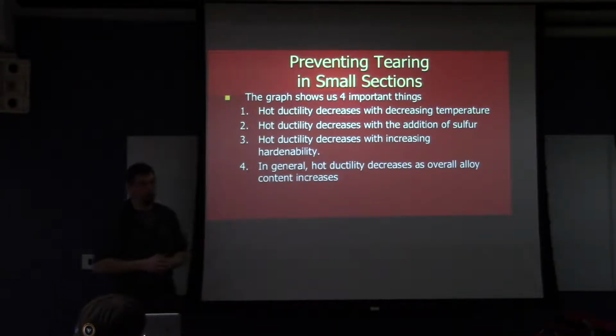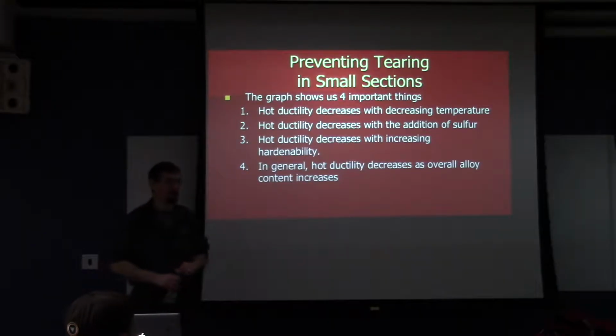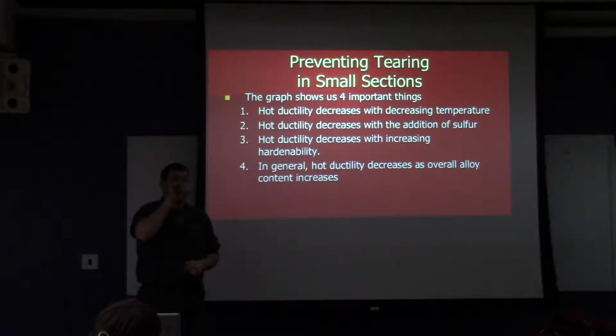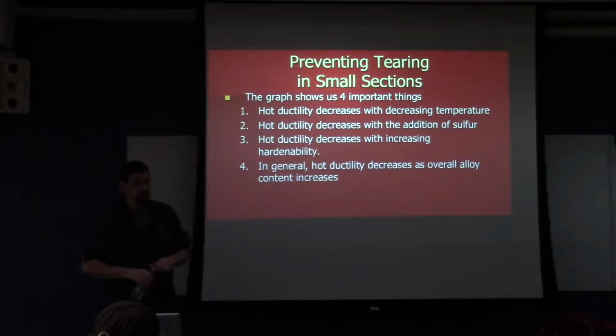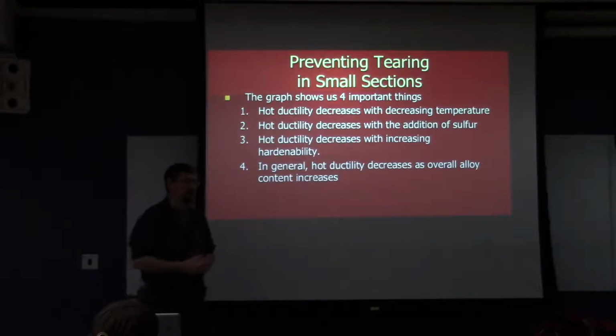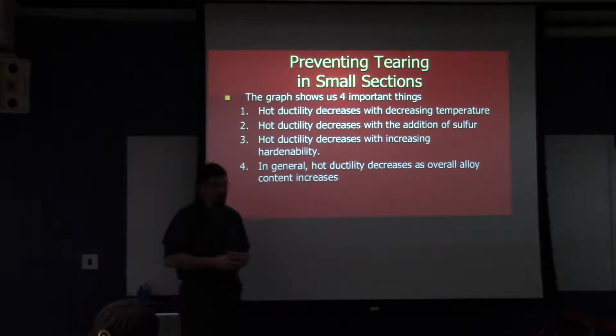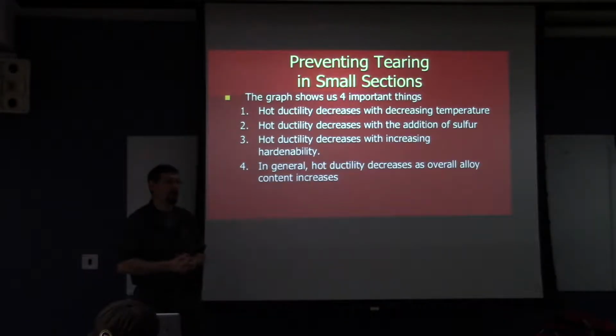Yes? So I've seen a lot of free machining alloys with lead. Is that equally forgeable, or does that start getting your grain boundary melting? Well, it is something that can be hot worked, but we don't work it at Scott Forge, so I can't tell you from any personal experience about that. My assumption would be that it would be at least as difficult to work with as the resulfurized materials. I don't think that you find a lot of the leaded steels around anymore because of the environmental issues associated with getting the lead into the steel and then how you deal with the chips and so forth afterwards. Leaded steels used to be really common because they were easy to machine.